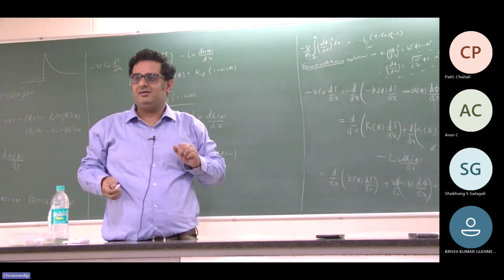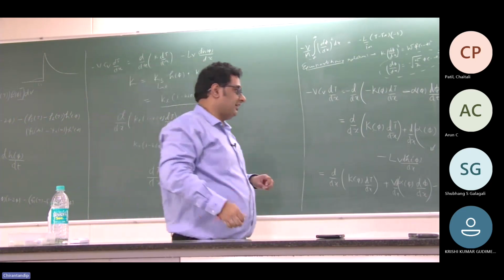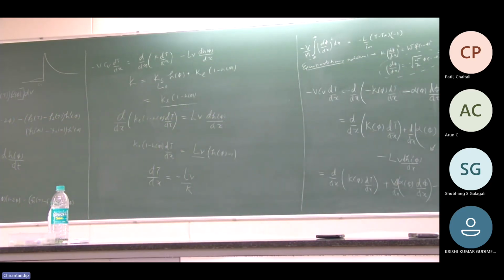So that we can correct in the C field itself, right? The point is this: I can write an equation for C as a function of mu. It's the same; the correction you get is not going to be different. It's still going to be a flux that you add to the diffusion flux. The final shape of the equation that the J will take will be exactly the same if you start from a C equation or the mu equation.